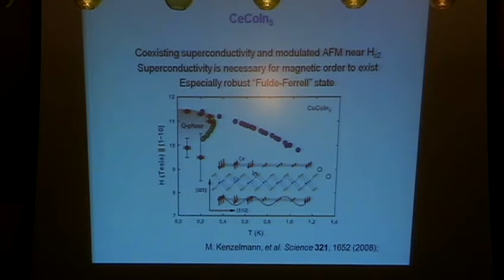So here's an example of one which has also been a bit of a conundrum, cerium cobalt indium 5. This is a superconductor, an interesting d-wave superconductor at a temperature of a couple of Kelvin or so. It's a type 2 superconductor, and in a magnetic field, the transition temperature drops, this is Hc2, down to zero. The interesting thing that happens is that in the vicinity of this boundary here, a new phase was seen. And the phase boundary was discovered by a variety of means. It was originally suggested to be Fulde-Ferrell, but it turns out on closer inspection, it's not really, it's a spin density.